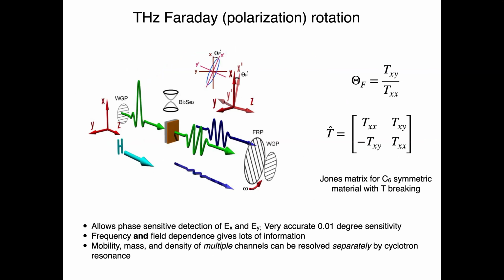Good. Now, one really important quantity that we can use to understand materials, and this is something I'm quite excited by. When I present this to people who are not experts, they feel this part of the topic is a little prosaic. But one of the things that's really useful for us is to understand how the polarization of the light is affected when it's transmitted or reflected through the material. So we've spent a lot of time in my group developing very accurate terahertz polarimetry techniques. That's the part where people's eyes start to glass over a little bit. These are ways to measure the polarization in the terahertz range quite accurately. And when we started this, state of the art was 1 degree, which is not bad, right?